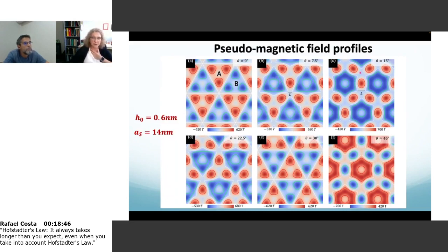When I go to 15 degrees, the thing gets worse. The anisotropy between up and down gets larger. The magnetic field hill becomes very, very high, and the valley is shallower. The equipotentials here form lines that have larger symmetry than these ones. This figure has a larger symmetry than this one. And what I notice is that these regions start to develop the structure of a triangular lattice, while the hill regions develop a structure of a Kagome lattice.